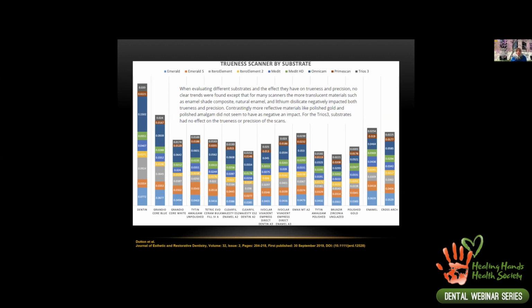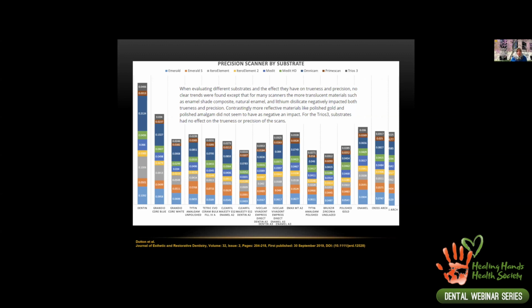So what does it tell us? Both from a trueness and precision standpoint, knowing that, for example, polished gold didn't really affect it, we have to really make sure that we polish our rest areas if we place them on these metals. Knowing that reflection really doesn't negatively affect is an important finding. And knowing that in certain scanners, the substrate doesn't have much of an effect on the trueness and precision.